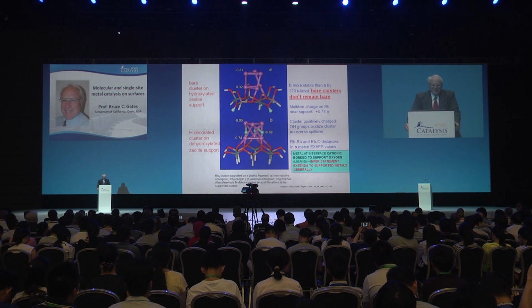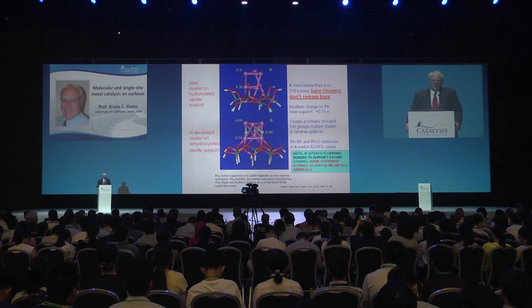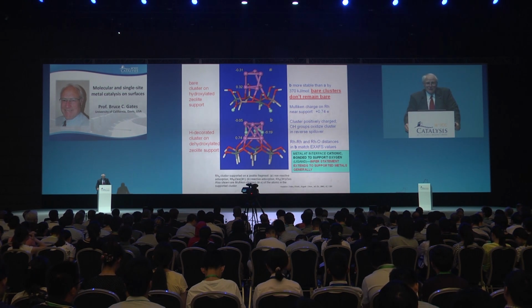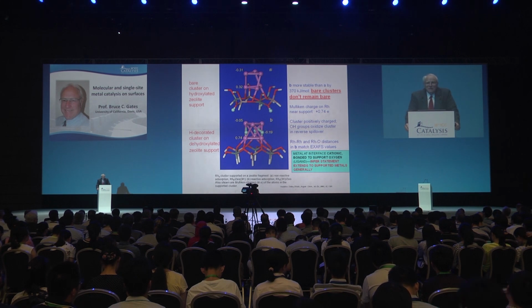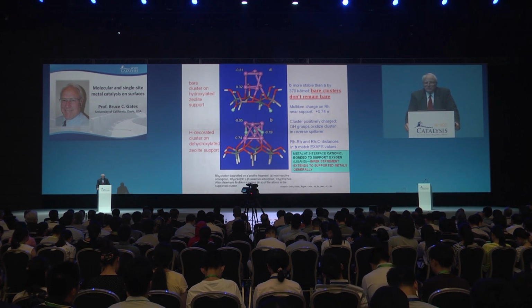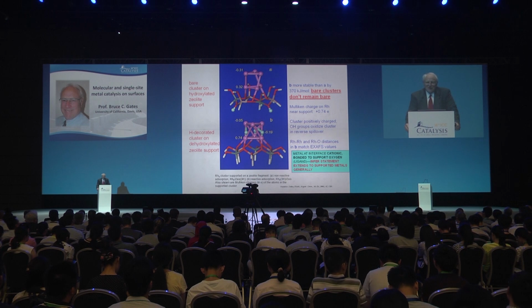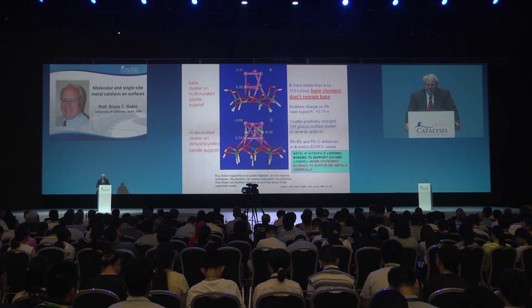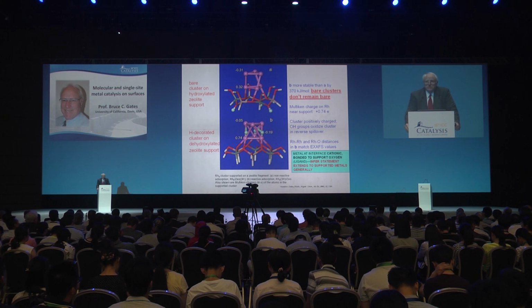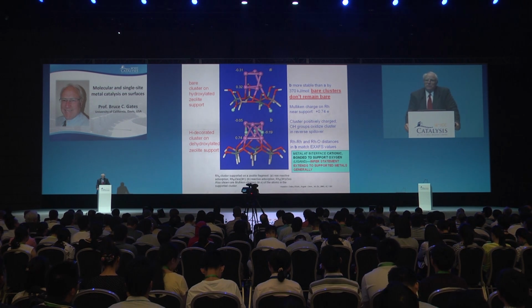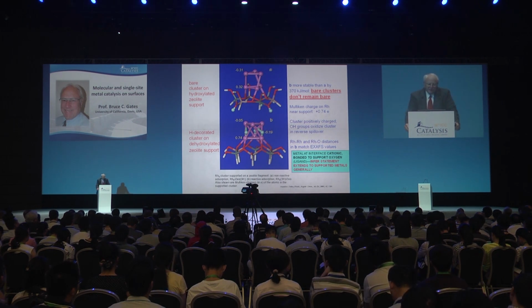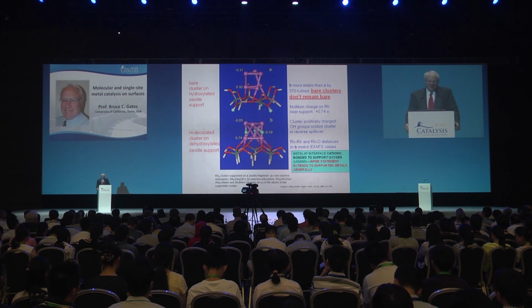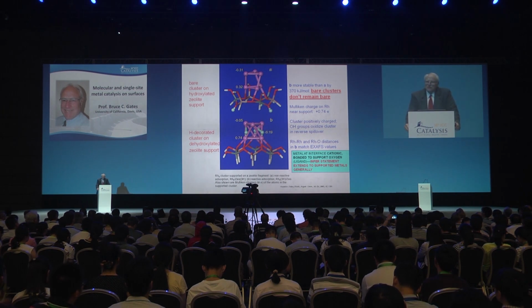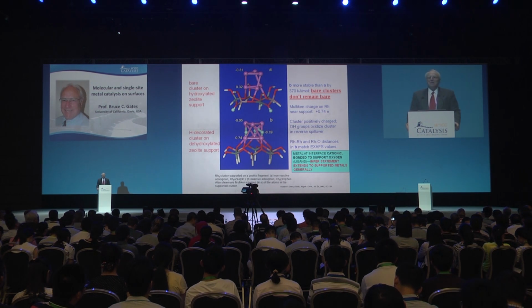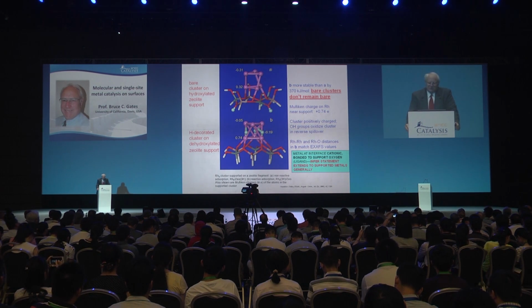Then they started doing calculations for clusters that were no longer bare and found that those clusters on realistic supports having hydroxyl groups are highly reactive. They form metal hydrides, which are much more stable than the bare clusters. And they also found charged rhodium at the interface, and then they started finding structure parameters in good agreement with the experiment, the EXAFS spectroscopy.